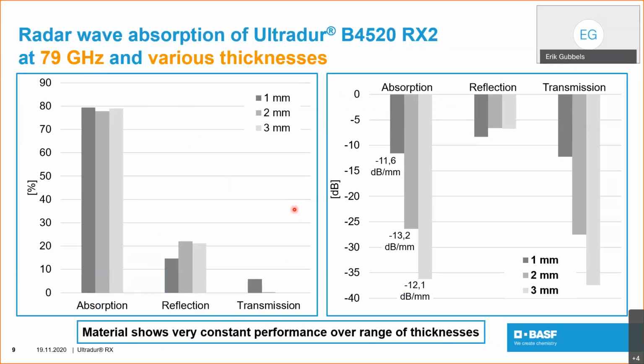We brought one example for the thickness dependency of a material, for the B4520RX2. Again at 79 gigahertz, but this time at various thicknesses ranging from 1 to 3 millimeters. One can see that actually the absorption remains relatively constant, and there is only a small change in the reflection, where it's increased if you go from 1 to 2 millimeters, because at 1 millimeter there is this destructive interference occurring, therefore the transmission is a bit higher, but reflection is lower.